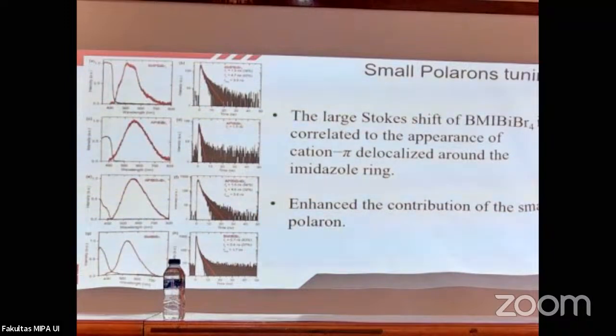And then if we go back to another class of system, it's jump back again. Which means here, I hope I can give you some idea: you tune something in the chemical structure, you end up with a different scenario. So we find a situation that, from the chemistry point of view, when you change the cation, the cation-pi delocalized, you change a bit the dynamics of the charge carrier within the system.